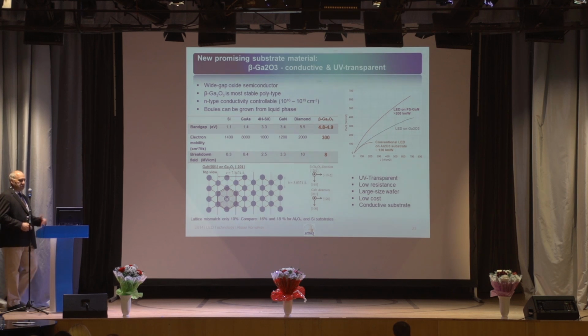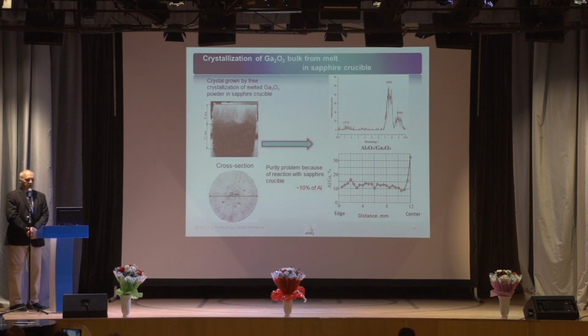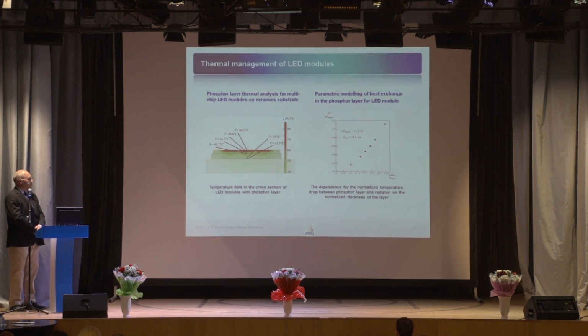Therefore, it is expected that the use of this gallium oxide material will also help a lot in the LED-related problems. And I report now that at Ioffe Institute and also in cooperation with our LED chair at ITMO, we already succeeded in getting first bulks of this gallium oxide using liquid phase processes. To the contrary of gallium nitride, this material can be processed using the liquid phase. So it is a big advantage.